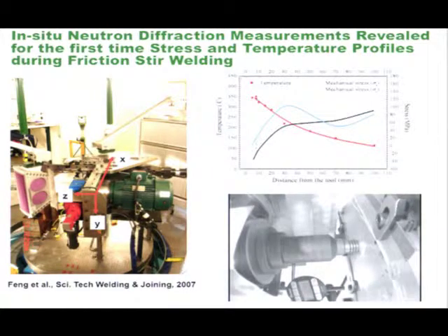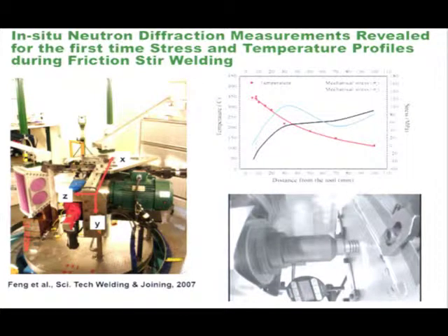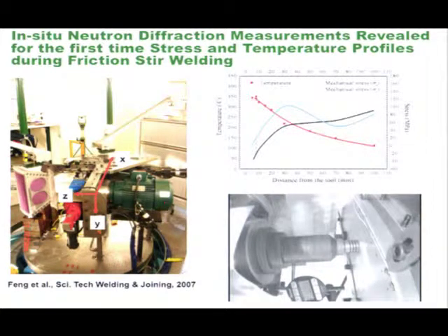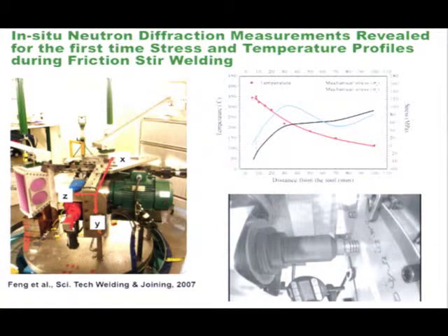During the measurement, the scattering volume is held at a fixed spot relative to the machine tool, and this specimen just moves, okay? So after that, we can measure the total strain as a function of different positions from the weld tool. So you can imagine you position the scattering volume at different positions away from the weld tool, and we can map out this